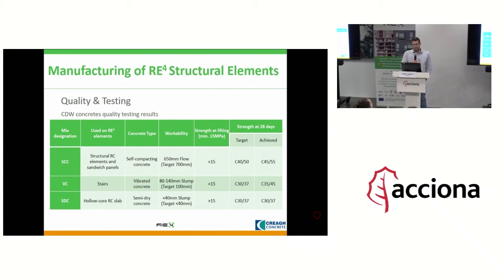During the entire manufacturing process, we check the quality and test the concretes. Here I'm showing a table of the results of the CDW concretes used in this project, and we can see that all the concretes performed very well. They achieved the lifting strengths within the normal curing times, and they achieved the target strengths at 28 days, with the self-compacting concrete and the vibrated concretes performing better than we anticipated.